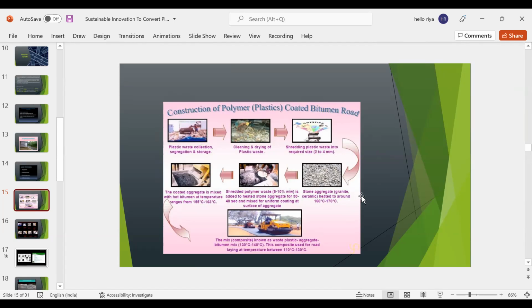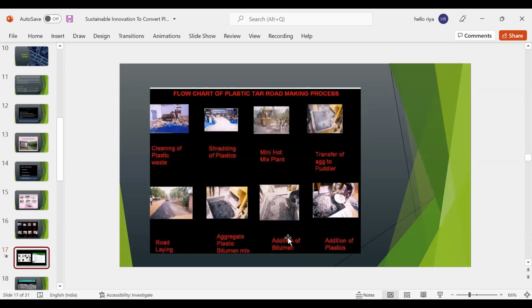This shredded plastic is set aside, and 5 to 10% by weight of the shredded polymer waste is added to the heated stone aggregate. The aggregate gets heated for 30 to 40 seconds and mixed with this shredded plastic waste at 160 degrees Celsius to 170 degrees Celsius. Then this material gets mixed into the hot bitumen at a temperature from 155 degrees Celsius to 163 degrees Celsius. This mixture is called the waste plastic aggregate bitumen mixture, and it is used for the construction of the plastic road. These are the basic steps which I showed you.